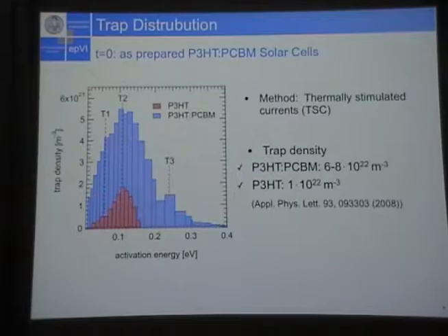What you do is fill the traps by shining white light on your device and cooling it down. When you stop at a very low temperature, say 10 K or 15 K, you connect your device to a very sensitive picoampere meter and just warm up. So you have a kind of T-start, T-stop method, and by choosing this T-start and T-stop,